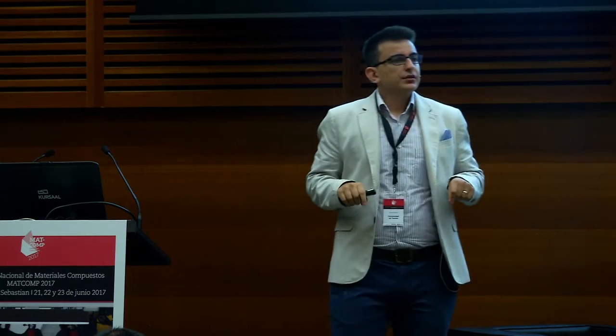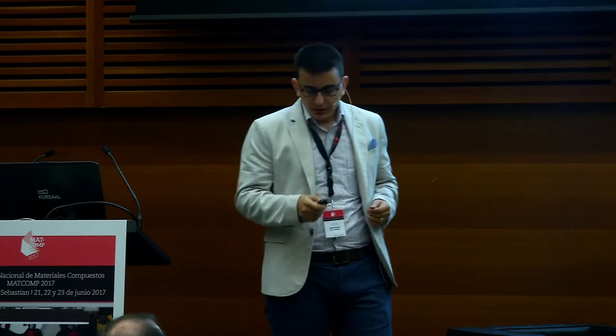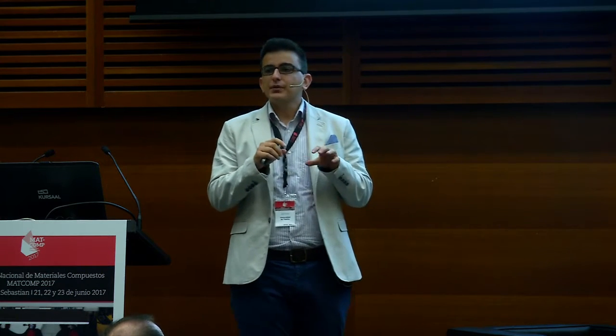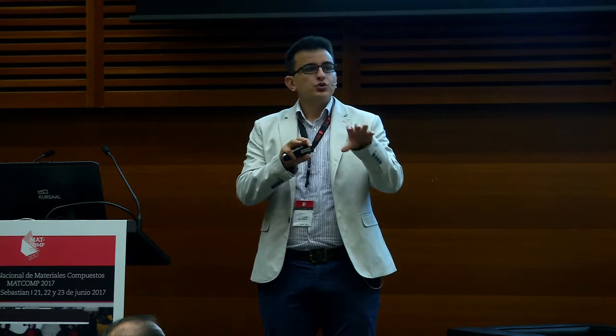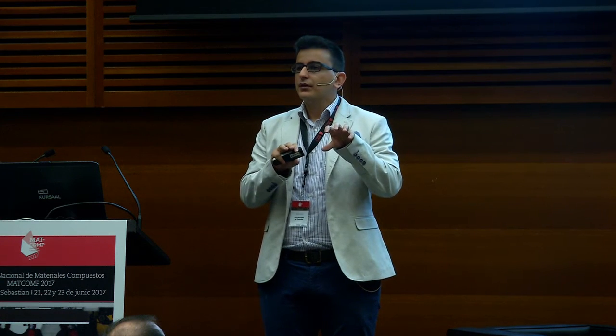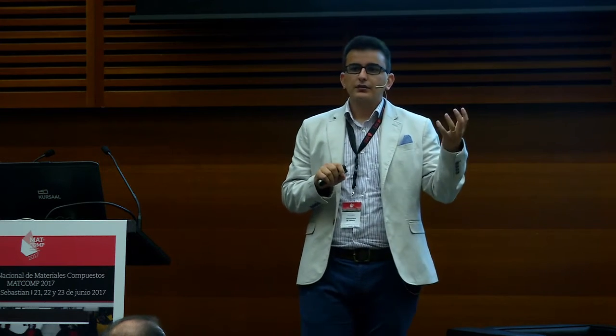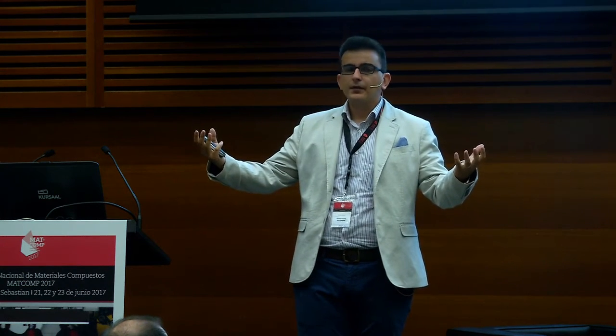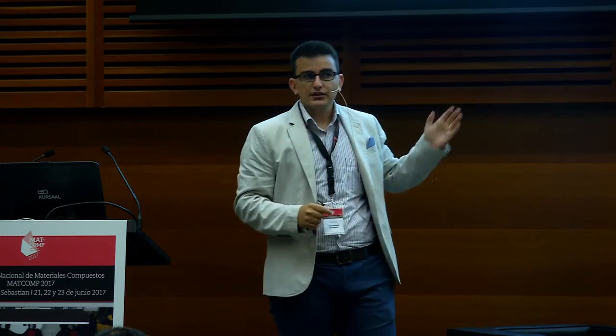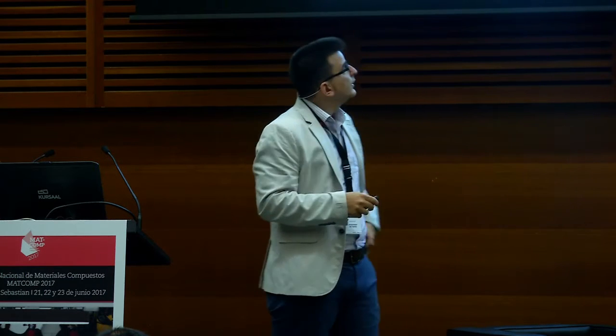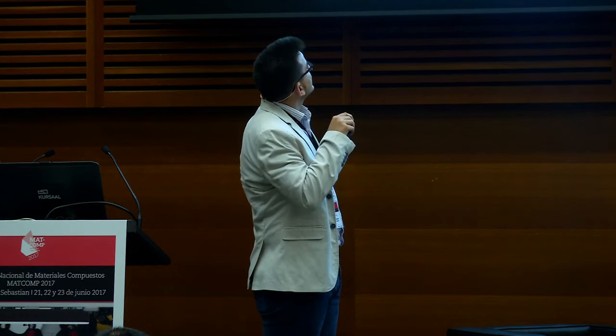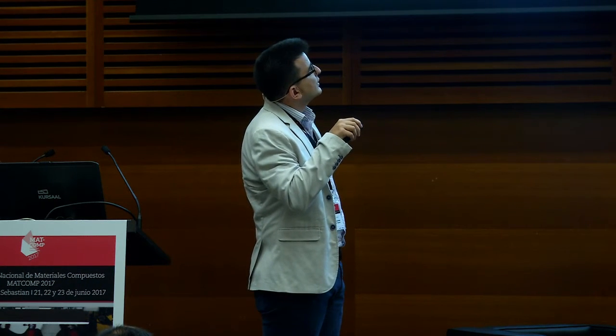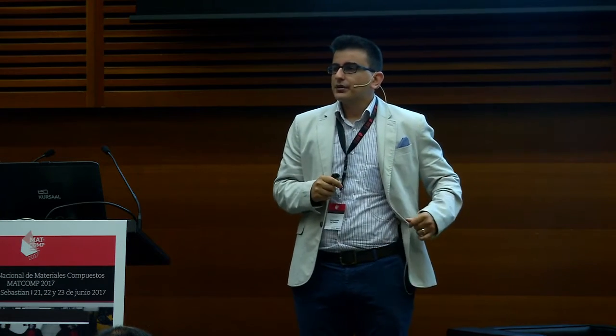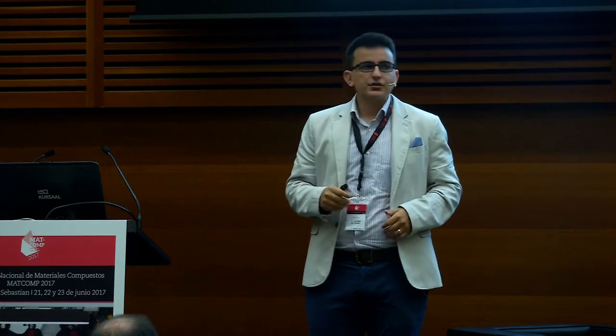So if you look at the internal structure briefly from micro-CT analysis, we do see some resin-rich areas between the fiber rovings. In principle, the fiber rovings should be aligned in between the guiding plate and the pulling unit. If this alignment is not perfect, the fiber rovings during the pultrusion can wander to a local place such that we have resin-rich areas with really low fiber volume content. And we do see these resin-rich areas here, and around resin-rich areas, we have severe fiber misalignment in the in-plane and out-of-plane directions.